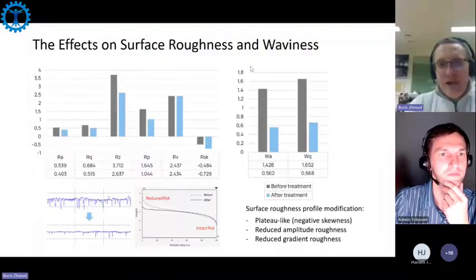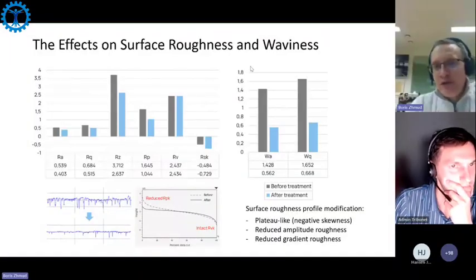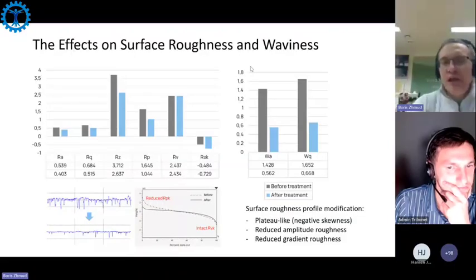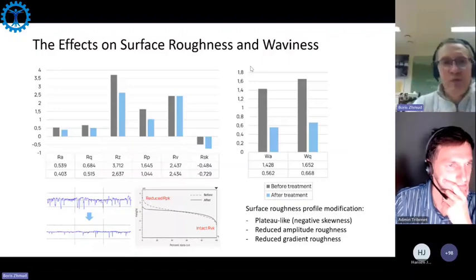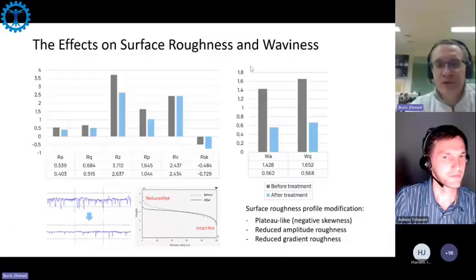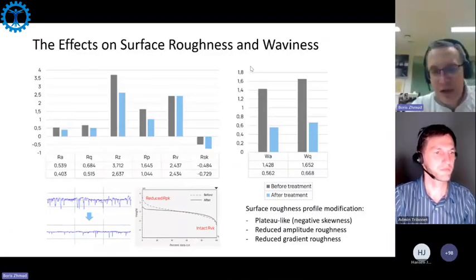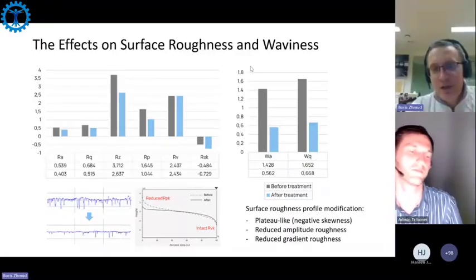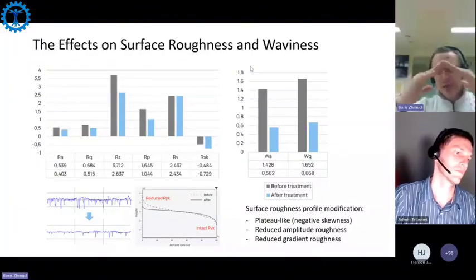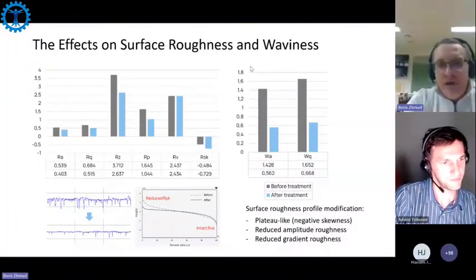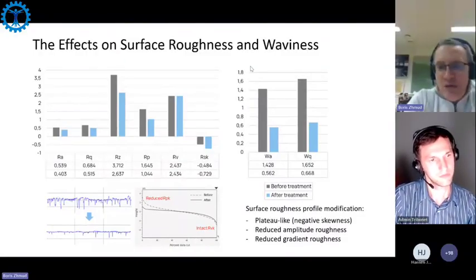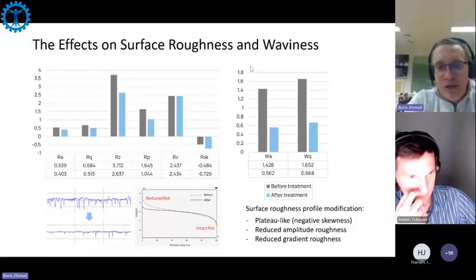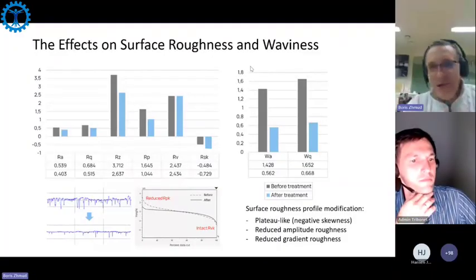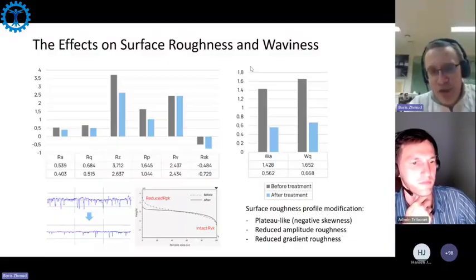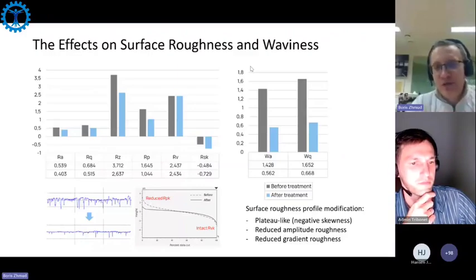First and foremost effect is effect on surface roughness and surface waviness. And this effect is actually not unique for mechano-chemical finishing. The same effect you can achieve by conventional super finishing. The only difference that you would require multi-step process. We get reduction in amplitude roughness. We get reduction in gradient roughness, which means that actually slopes of asperities are reduced. And we get also some reduction in waviness, which is also positive when it comes to noise excitation. But again, I repeat that when it comes to the modification of surface roughness profile, it's not unique for mechano-chemical process. It's positive side of mechano-chemical process, but this you can achieve also by other means.